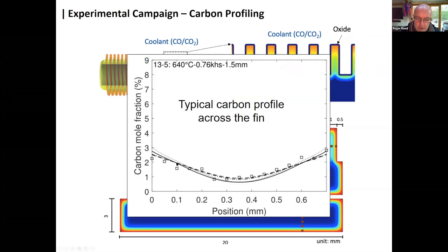So you can see here that F1 measures the carbon profile across the fin. So this is about 1 millimeter here. We, of course, couldn't measure easily the carbon in the ferrite, but what we could do was to do stereological measurements to deduce the carbon present from measurements made on the local carbide fraction. And that convinced us, you can see here our data and also the underlying models, that the fins were becoming saturated with carbon over time.